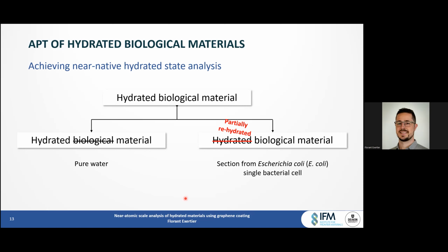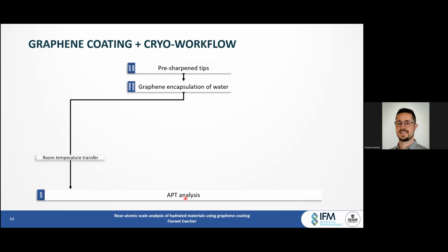And the samples used in this study were sections from single E. coli bacterial cells. So first, let's have a look at the study of pure water with graphene coating. So there several workflows were compared. So first, the basic one, if I may, where graphene encapsulated water on top of tungsten tips was transferred directly to the atom probe using normal room temperature transfer.